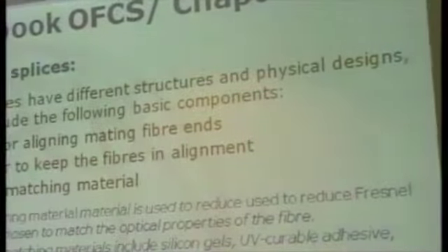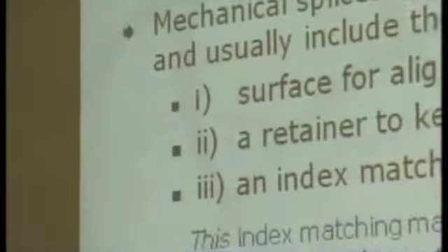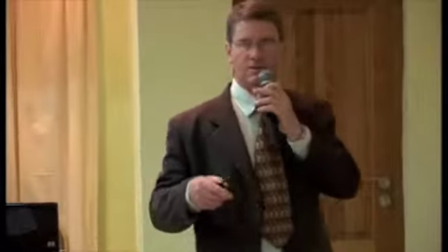One important thing to have in mind is that the index of refraction of these materials is very sensitive to temperature. Then they have a higher dependence on temperature, and this dependence is completely different from the glass. When we change the temperature by 10, 15, 20 degrees, the refractive index of the glass is still the same. When we change the same amount of temperature, some materials of this kind could change their index of refraction a lot. It could be a problem. Then it's very important to take care with the range of temperature that is established by the suppliers of this mechanical splice.